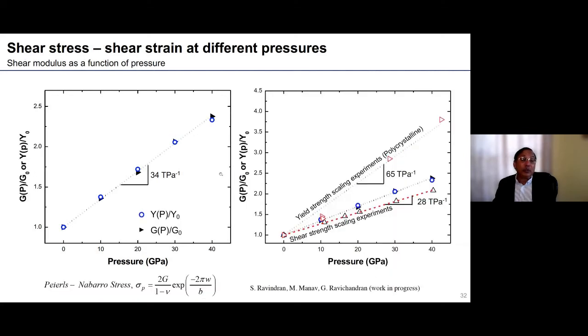And we can also obtain the scaling for the shear modulus from the molecular dynamics simulations, and they show the same values as assumed in the Steinberg-Guinan model, which is close to 34 per terapascal. As I mentioned, the Steinberg-Guinan model assumes 28 per terapascal, and in the experiments we are observing that the yield strength scaling is on the order of 65 per terapascal, and this is yet to be resolved.